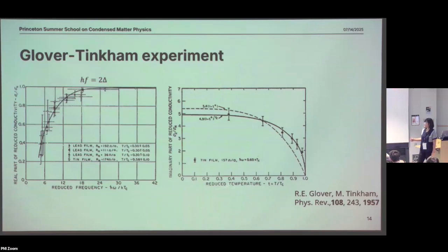They also measured as a function of temperature. Here, this is all below the transition temperature, from 0 to 1 T/Tc. And this is the imaginary part of the conductivity. So the left graph is about the dissipation, and the right graph is about the kinetic inductance. Here, sigma has this type of exponential increase as the temperature drops, and gradually it saturates again. This exponential increase of sigma is directly related to the S-wave pairing. For this type of gap, BCS theory can directly give you this behavior of the superfluid density, and then if you calculate sigma 2, it will have this behavior. So this was the very first experiment that proved the BCS theory and all the things about the superconducting gap.